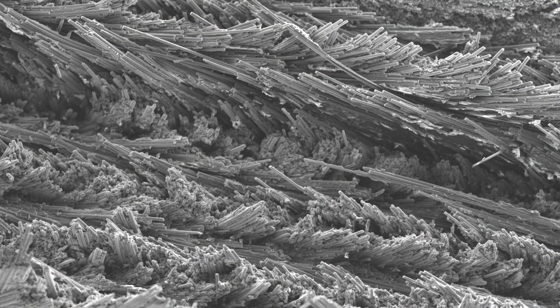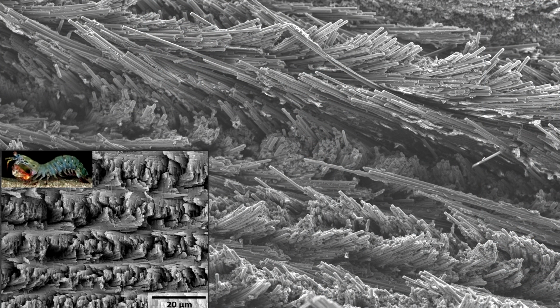So the next image that I'm going to show you, if you recall the mantis shrimp fracture surface, this is actually carbon fiber embedded in epoxy. And it resembles very closely the fracture surface of what you observe in the mantis shrimp. So it means that by leveraging this knowledge on how to arrange these fibers and obtain the benefit of the natural microstructure, you have a very nice translation, even though you are not doing a direct mimicking of the features found in nature.